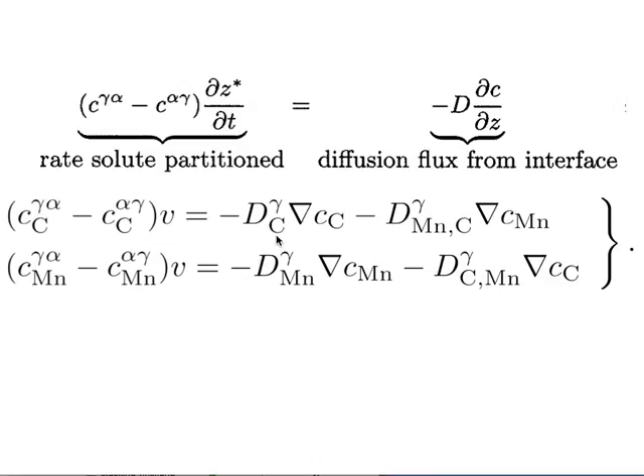This is the diffusion coefficient of carbon and the gradient of carbon, and the diffusion coefficient of manganese and the gradient of manganese. But the flux of carbon depends not just on its own gradient, but also on the gradient of manganese. So D with the subscript Mn, C is the interaction diffusion coefficient. We need a set of four diffusion coefficients to define the fluxes of carbon and manganese, okay?